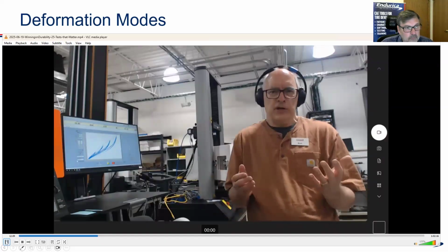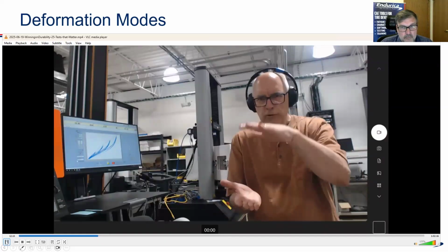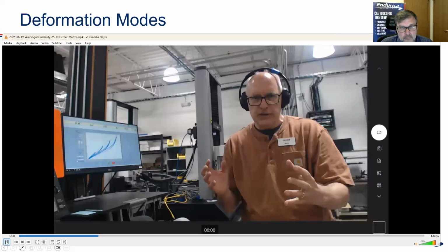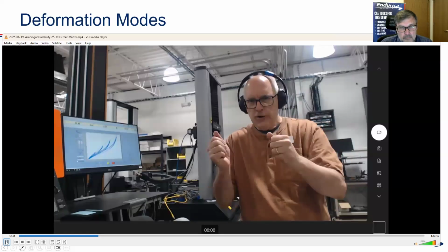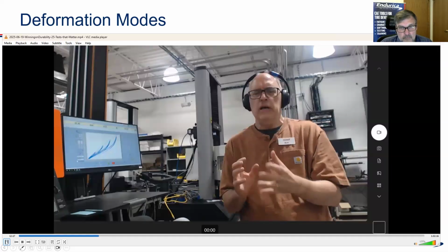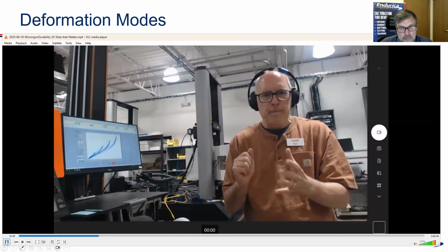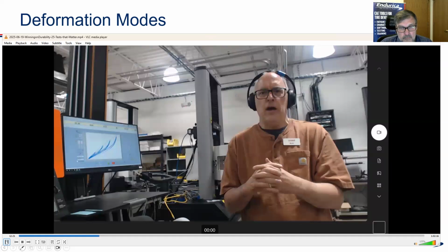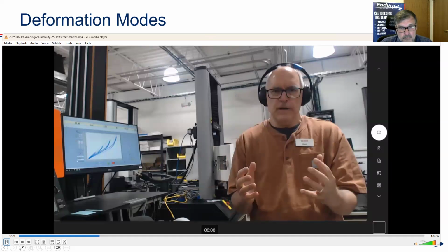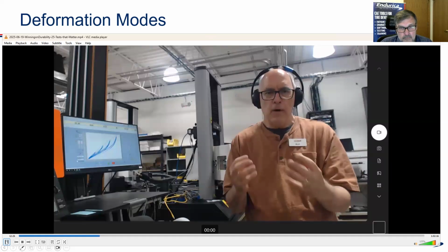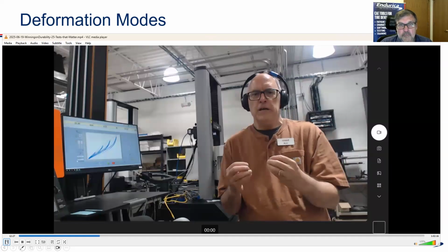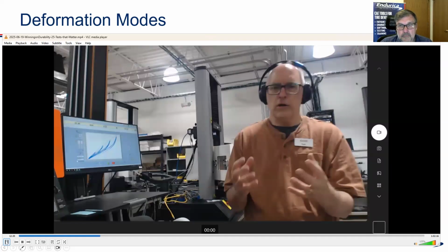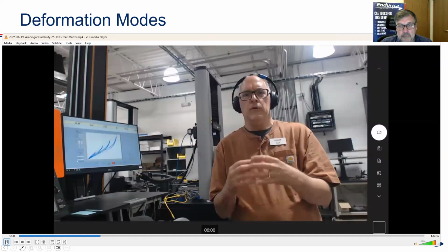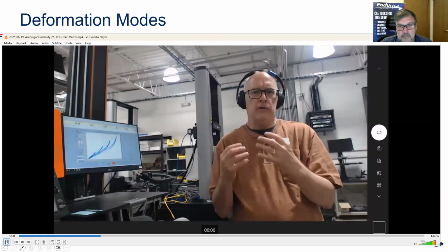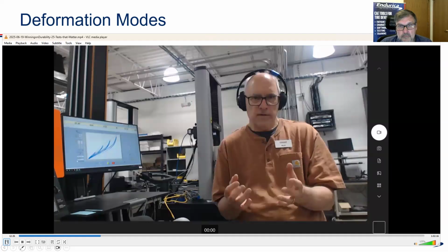Because the material is incompressible, as soon as I compress it one way, it goes other directions. If I shear it, there's always some tension, there's some compression. It's always big, messy business in there. So we have to have hyperelastic models, which are awesome. However, hyperelastic models need multiple data sets in order to characterize them well. If you don't have very much data, you have to use hyperelastic models that are not very descriptive.